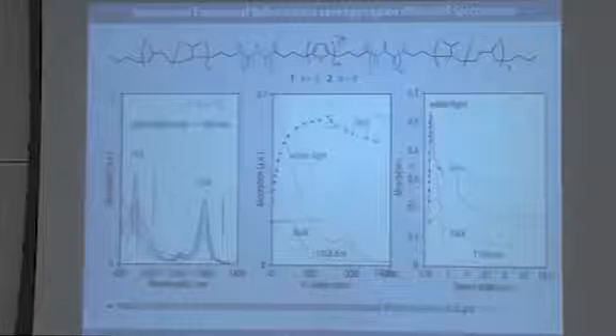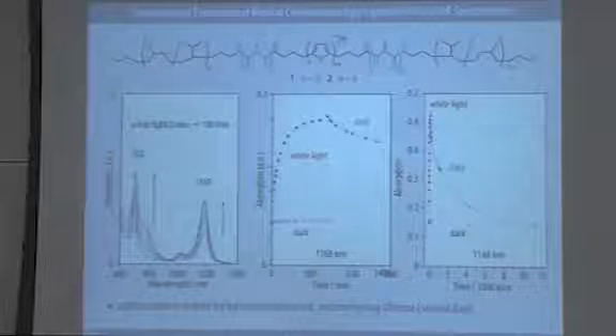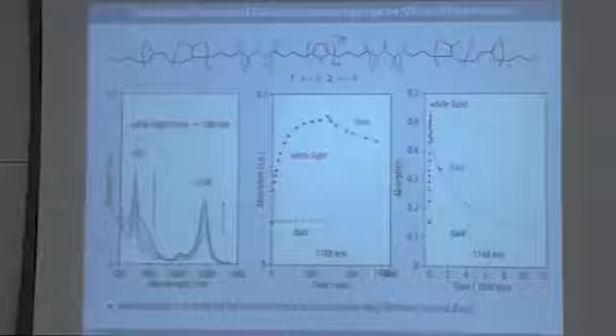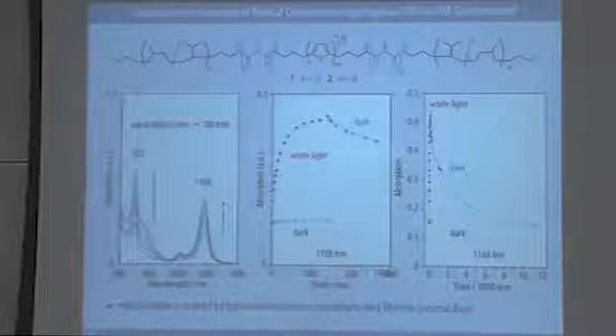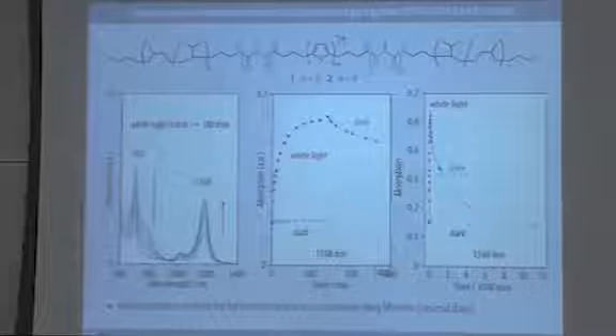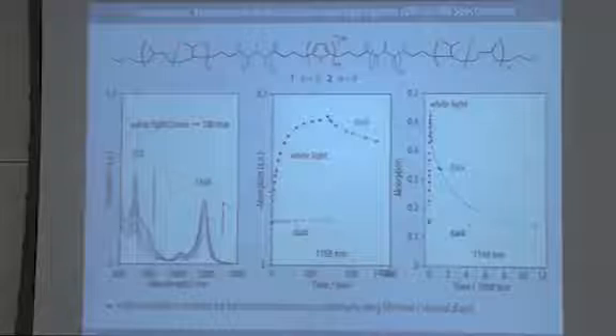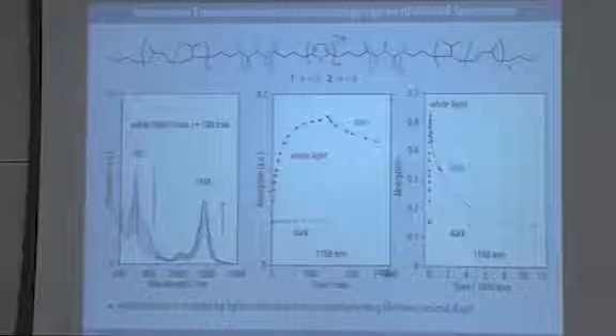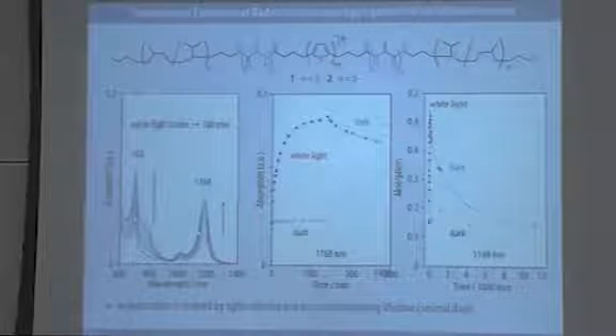We have then investigated what could be the generation. We excluded oxygen. We tried our best to exclude other inadvertently present oxidants. And we then found that actually these peaks are generated in a light-induced process.